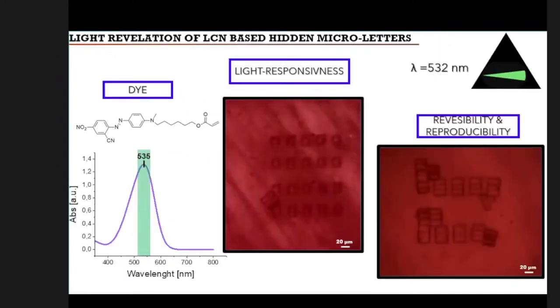Then I inserted in my monomer mixtures also a dye in order to demonstrate that I can obtain a multi-responsive material. In this case, as you can see, the array can be contracted under light, and the process is reversible and reproducible. So in this case also I performed a better system because the time scale changed from minutes to seconds, milliseconds, we can say.